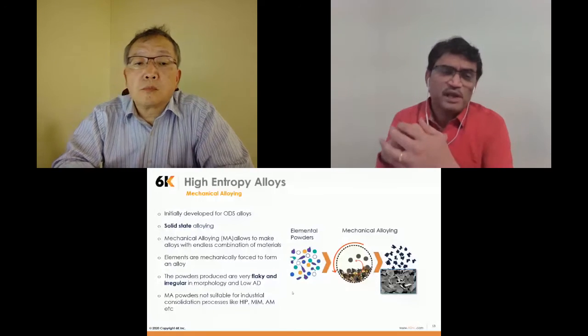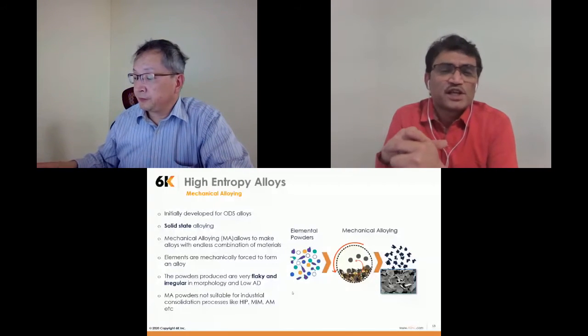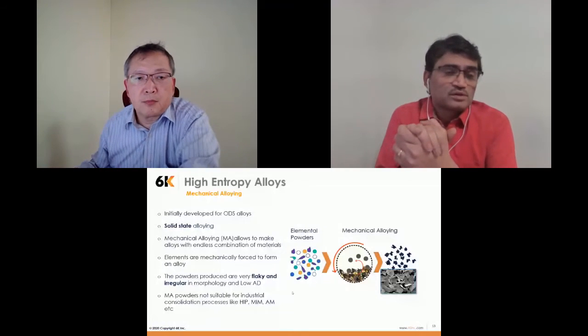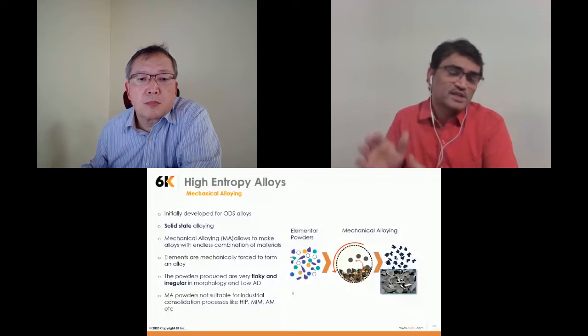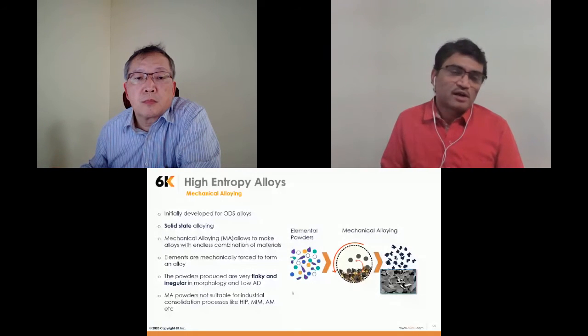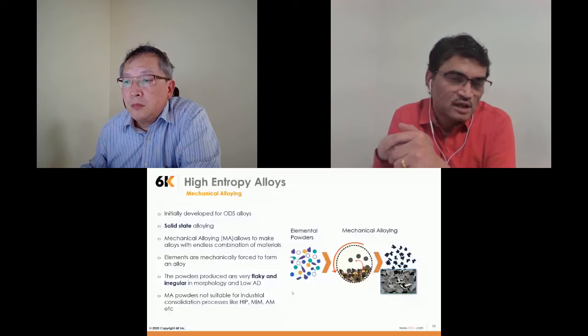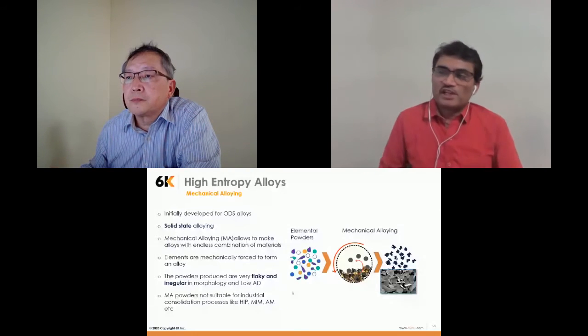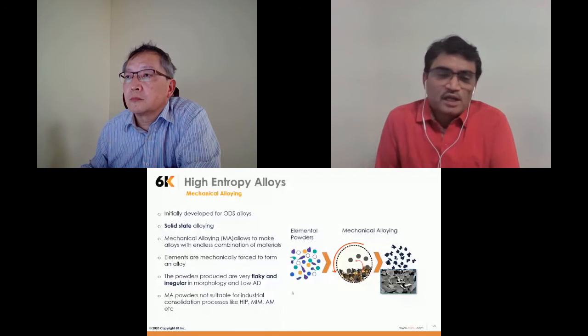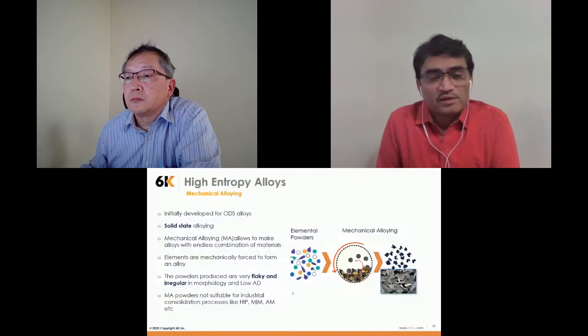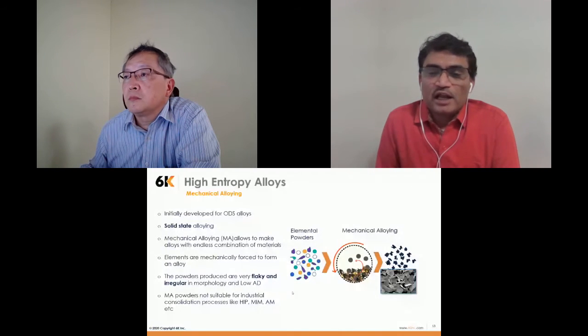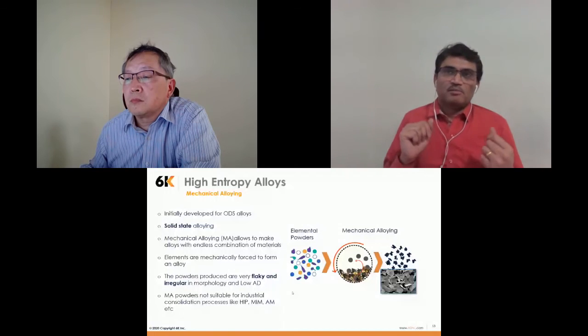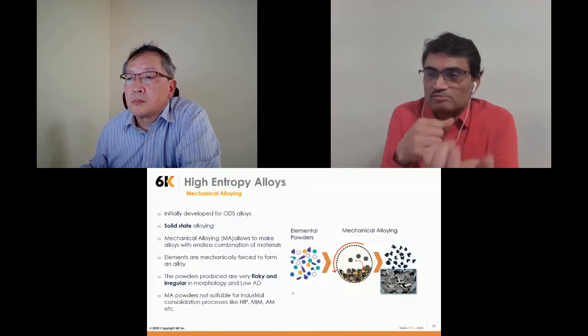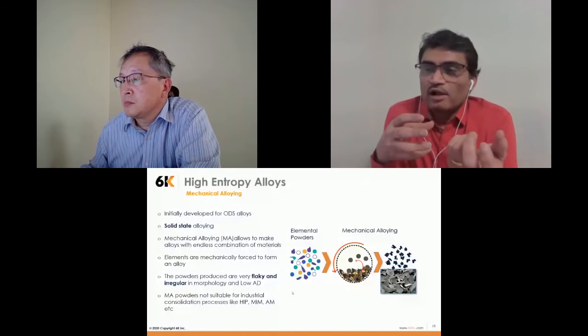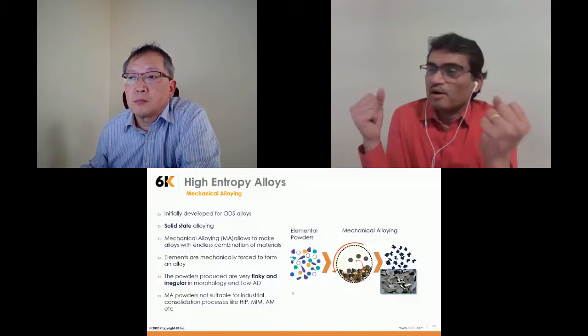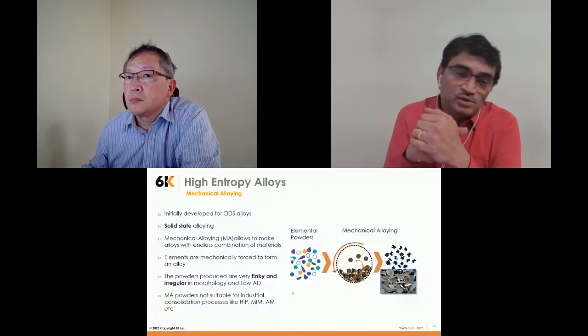Mechanical alloying is a process that was initially developed for oxide dispersion strengthened alloys, ODS alloys, where the alloys are mixed with very fine or nano-size oxides, and then they are producing composite ODS alloys. So this is basically a solid-state alloying process, which means that there are endless compositions that we can manufacture by mechanical alloying. It depends on the mechanical or kinetic energy of particles bombarding each other, or they're mechanically forced to form the alloys.